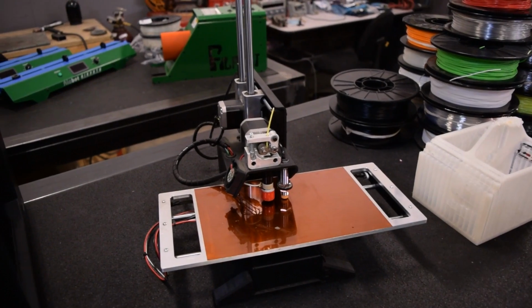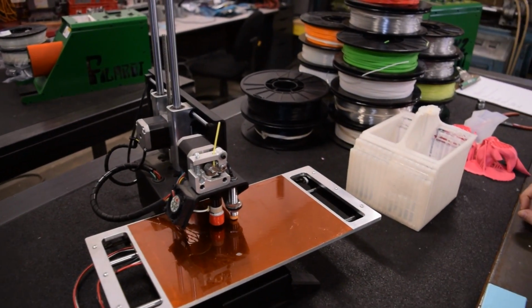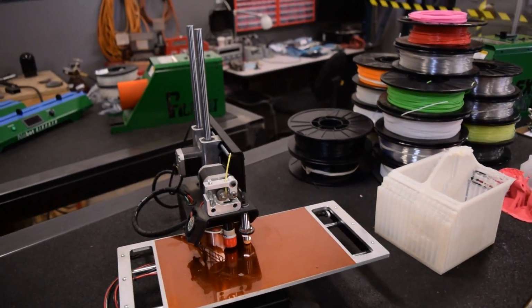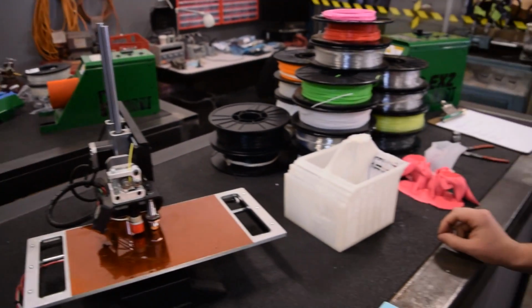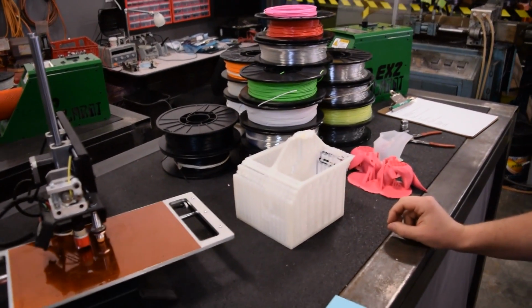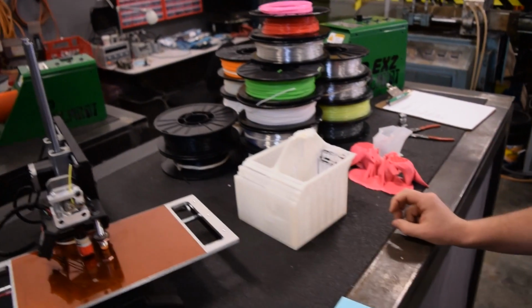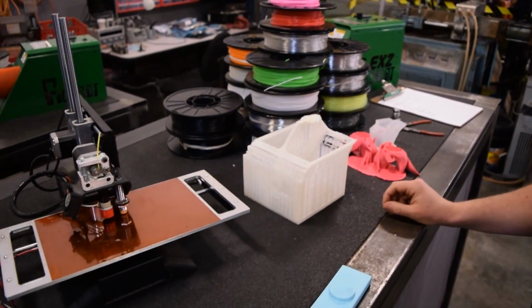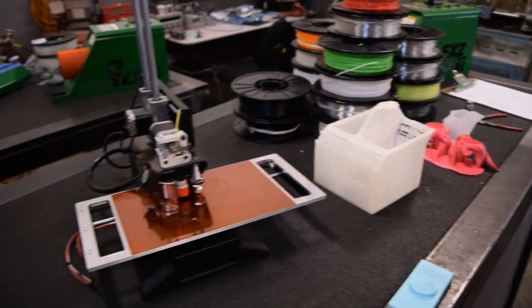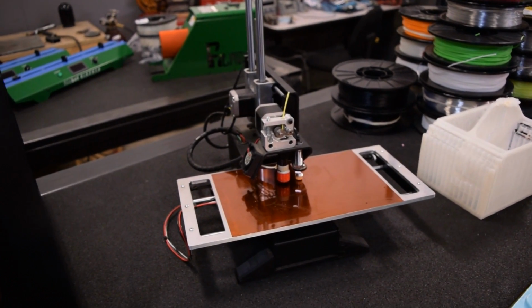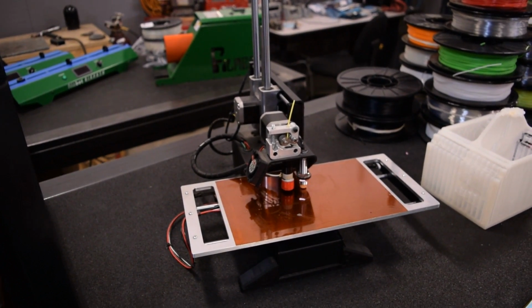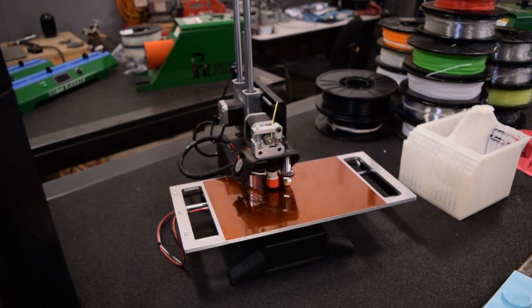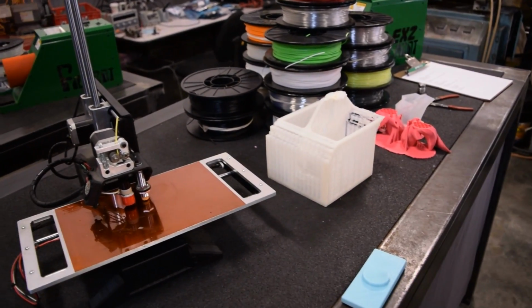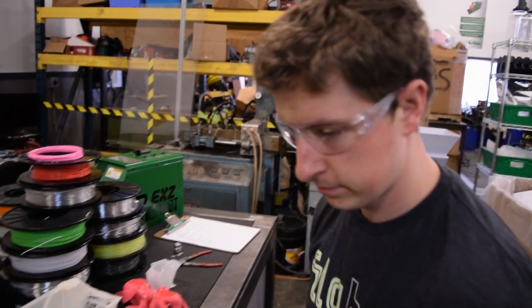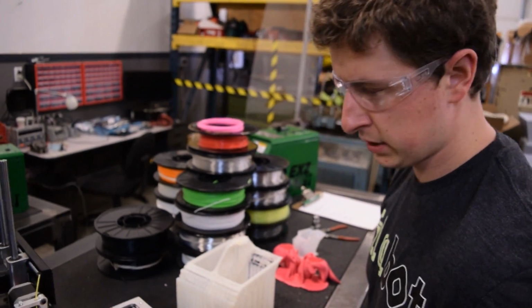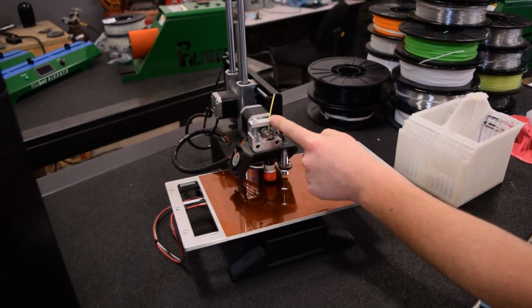Yeah, so if your temperature is too low, your melt flow will be too low, which means the polymer is thicker. So if the melt flow is low, that means the polymer is thicker when it's melted, and that's going to limit how fast you can push it through the extruder. And if your temperature is too low, it's going to make the melt flow lower. Right. Which will then make the extruder slip.